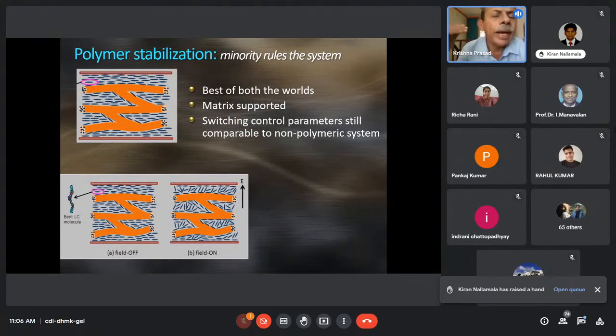What we talked about was a PDLC system, or polymer dispersed liquid crystal system, wherein the polymer content is significantly high. People typically talk about 60:40, 60 of the polymer and 40 of the liquid crystal by volume or weight. Densities are comparable in the systems. So you're talking about a large proportion of the polymer, and although it can be switched conveniently between scattering and the transparent states, the drawback of such polymer dispersed liquid crystals is that the voltage you need to apply to the system is pretty large. And because of these large voltages, even though the liquid crystals as well as the polymers are insulators, the power consumption by these devices is not insignificantly small. Apart from that, the quantity of the polymer that you are going to have can become brittle over time, and this creates situations which are not conducive for commercial applications.